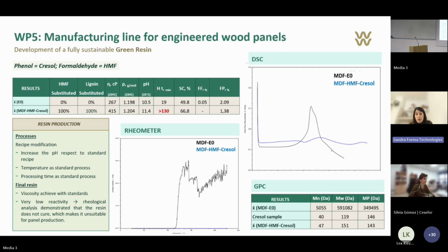This can be proved with the rheometer. As you can see, there is no significant curing peak, and the modulus remains near 0 through the temperature range. Moreover, with the DSC it's possible to observe that the degree of curing or cross-linking is far lower than the standard resin. Even the GPC shows shorter polymer chains for the cresol samples, meaning less extensive polymerization compared with the standard resin.